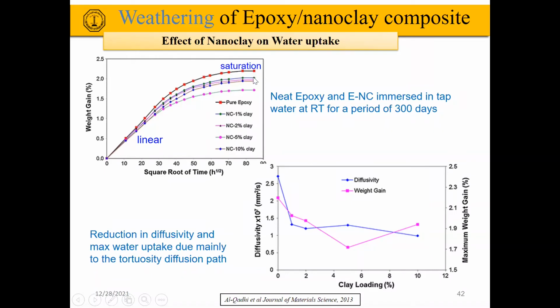But the addition of 1% clay reduces the water uptake. And you can see also that the water uptake starts to saturate around 200 days of exposure to, this is tap water actually, at room temperature.